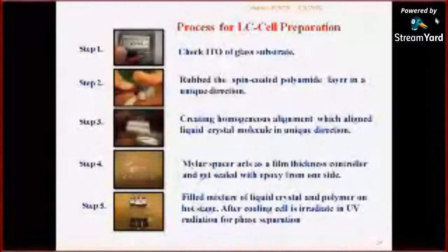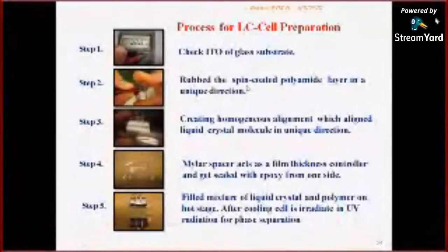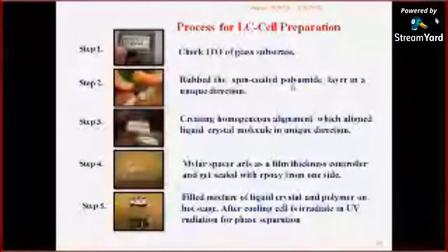So these are the preparation methods to prepare the liquid crystal displays. First of all, we check that these displays are made of ITO, and we check the glass substrate ITO using a multimeter. Then we introduce alignment by using a spin coating unit, coating a polyamide layer on that substrate.